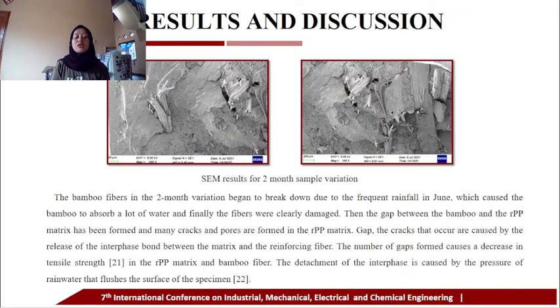And this is the result for the 2-month sample variation. The bamboo fibers in the 2-month variation began to break down due to the frequent rainfall in June, which caused the bamboo to absorb a lot of water, and finally the fibers were clearly damaged. Then a gap between the bamboo and the recycled polypropylene matrix has formed, and many cracks and pores are formed in the recycled polypropylene matrix.